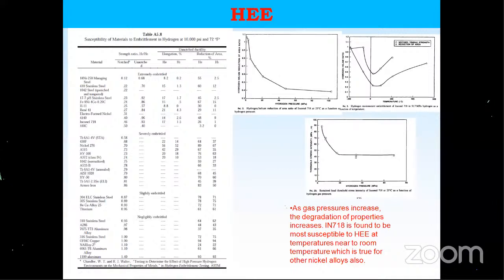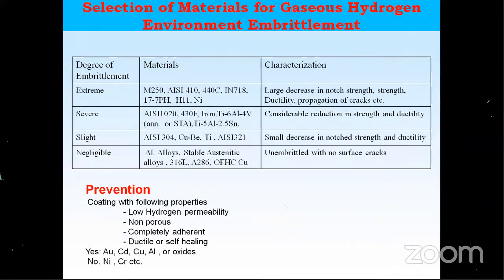Okay, good. Then we have the stress intensity. Everything comes down, fracture toughness, all this comes down. So for 718, they have done some coating and they found they have solved the issue. These are the materials shown in the table. We have negligible effect in materials like aluminum alloys, austenitic stainless steel, OFHC copper, and so on.